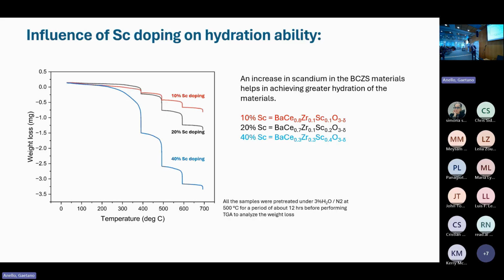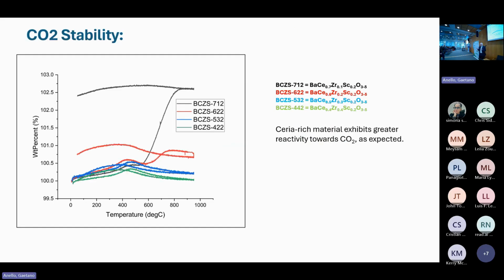But as you add scandium, you get more water absorption, you get more proton conduction. So scandium is quite beneficial. It can give us more mixed conduction than yttrium. The question always asked about barium perovskites is stability. So you can see the one in black, which has got the highest cerium content, forms barium carbonate.